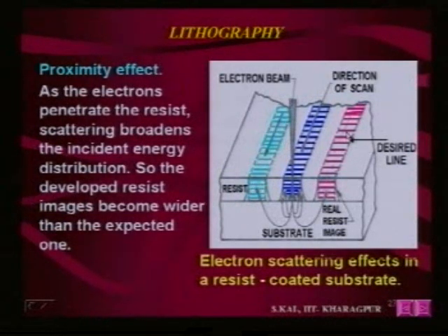Now you see, if these lines are very close, then because of the proximity effect, what will you get? The gap may vanish. If this line, say blue, and this red line are very close to each other, because of the proximity effect, the whole thing will be exposed. So this region may vanish. This is one of the problems in lithography, the proximity effect. It is very critical when you think of fine line lithography, that is, in VLSI technology, when the feature size is in the submicron region. But if the gap between the two lines is, say, 8 micron or 10 micron, then there is no problem. It will be a little bit widened, but it will not pose a lot of danger.